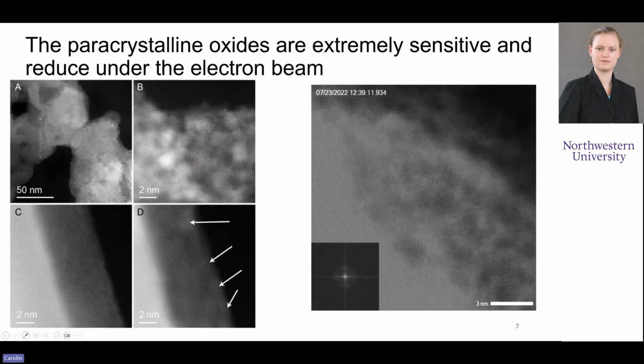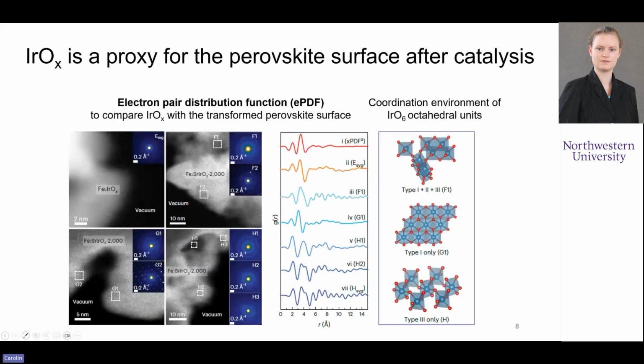So now that we have a way that lets us look at these materials and make sure we capture the phenomena that we want to see, let's compare the iridium oxide to our perovskite surface. And so as we use these catalysts in electrochemical systems, one thing to note is that we can't use the X-ray pair distribution function anymore because in order to use them as catalysts, we mix them with carbon black, we put them on carbon paper, and all the X-rays that we would see coming out afterward, all the signal would be from the carbon. And so what we do instead is we use the electronic equivalent of it using the electron pair distribution functions coming out of our electron microscope.